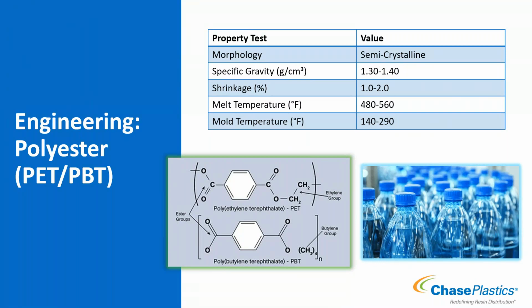The difference here between your PET and your PBT is that your PBT has 2 additional CH2 groups on the backbone. That's the only difference there. But because of those 2 additional groups, it makes it a longer chain for the PBT, and it makes it a little bit more mobile - it's easier to move. You'll see how that comes into play on the next slide a little bit.